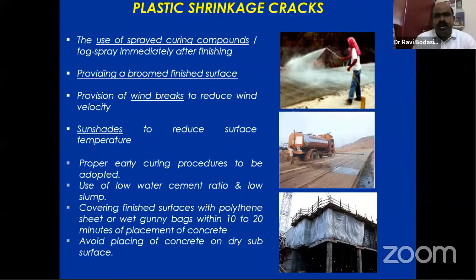So for that, immediately you have to take the following measures: use spray curing or early curing, and a wind break should be given to avoid the wind velocities, early curing, and have low water cement ratio and low slump, covering the finished surfaces with Hessian cloth, and avoid placing concrete on dry subsurface. Why? Because when placed on dry subsurfaces like roads, the element acting as the subsurface will absorb the water in the concrete immediately after placing. What is the water remaining in the concrete after absorption by the subsurface? It won't react with the concrete. That is the reason plastic shrinkage cracks may occur.